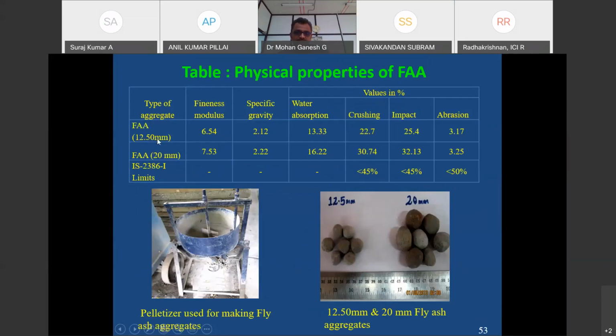Now the fly ash aggregate, already manufactured fly ash aggregate, we have compared with our aggregate. So these are all the values for our fly ash aggregate concrete. Here the pelletizer, a small pelletizer, we have fabricated ourselves, and with fly ash, nearly around 10% of cement we have used as a binder and manufactured two different sizes of aggregates. This diagram shows the 12.5 mm size of the aggregate, and this is a 20 mm size of the fly ash aggregate. These are all the tested values of our fly ash aggregate: fineness modulus, specific gravity, water absorption, crushing, impact, and abrasion. It should be at par with our fine and coarse aggregate. Then only we have to use this in the concrete structure.